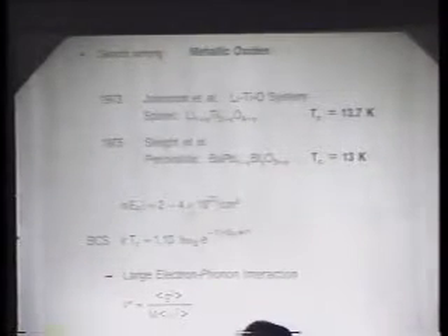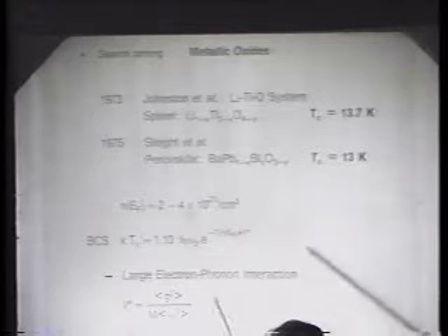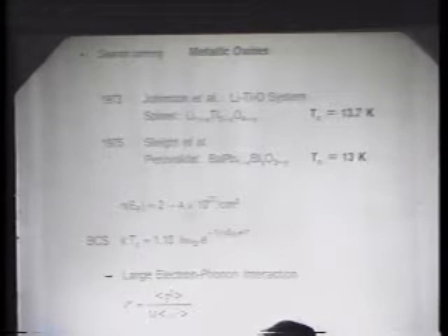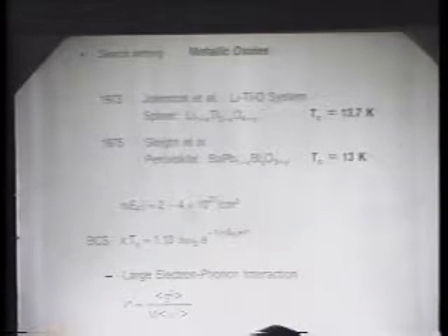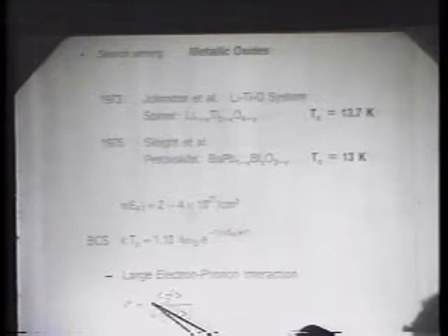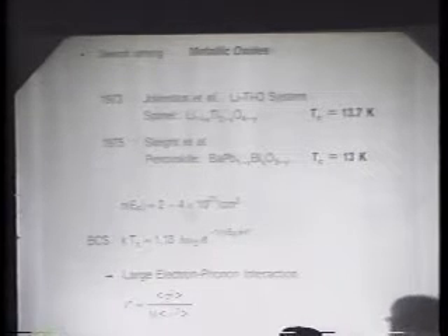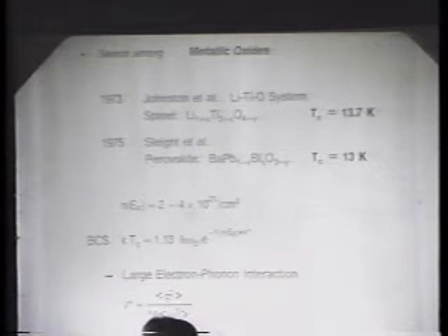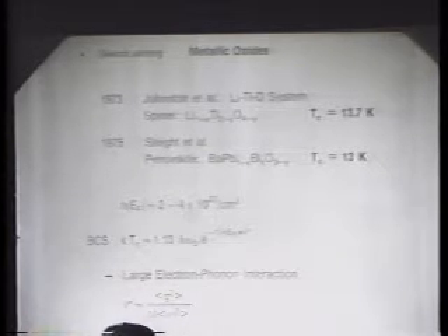And this was remarkable because this carrier concentration multiplied by the electron-phonon interaction is essential in a normal BCS superconductor; the formula stands here. So that means that this electron-phonon interaction had to be very large, and one could expect that if one would try some other oxide, one may do better than that. So this was part of the concept.